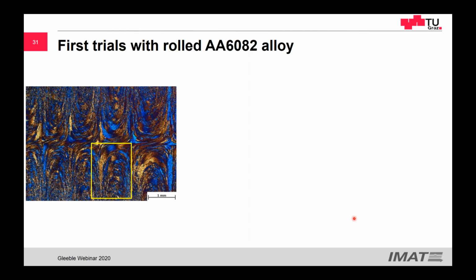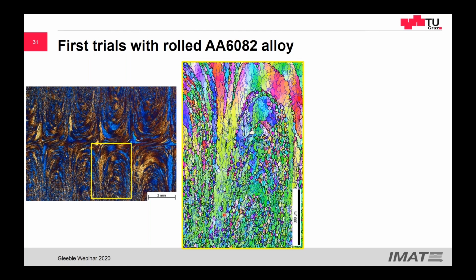And we were really very frustrated because we were waiting for a very homogeneous, fine microstructure, and this is what we got. And it's very nice for, I don't know, for putting in the living room, but it's very complicated to understand. So we did EBSD of this part, as you can see here, and we have seen that the new grains, the very small recrystallized grains, have a very strong texture, so all the same color. Let's put it in these words.